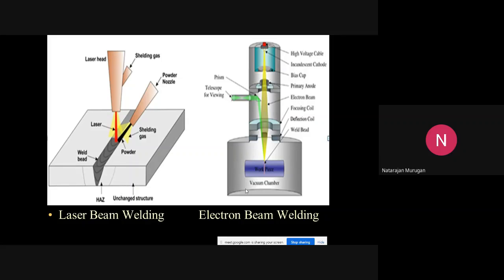Approximately 1 kilowatt of laser costs 1 crore. Think of that. With the 4 kilowatt laser you can weld up to 6 or 7 mm. I have seen a 25 kilowatt CO2 laser at Luleå University in the north of Sweden, when I visited in 2007. There you can weld up to 32 mm with the 25 kilowatt laser. Practically, as the power wattage is increased, you can weld more thickness in a single pass.